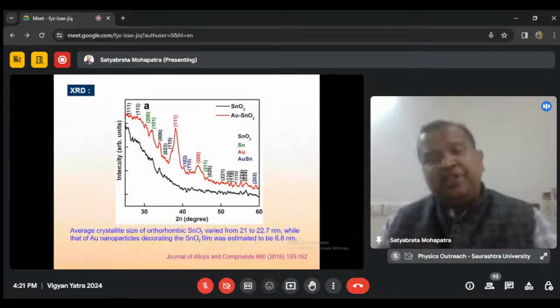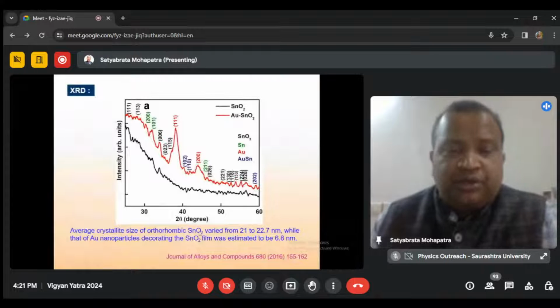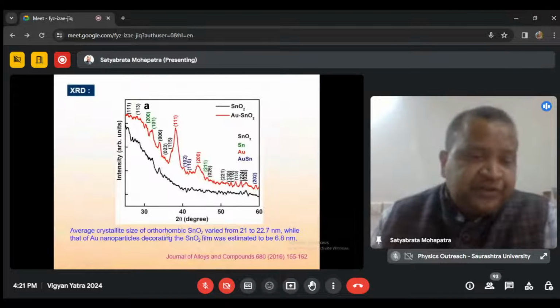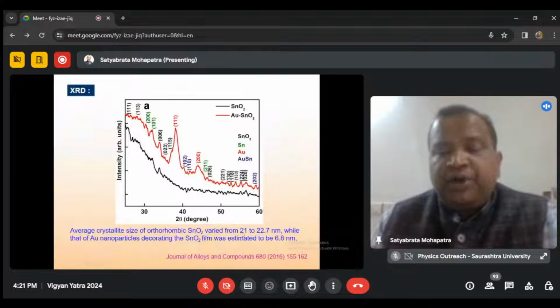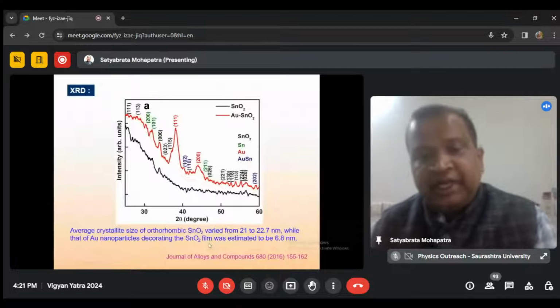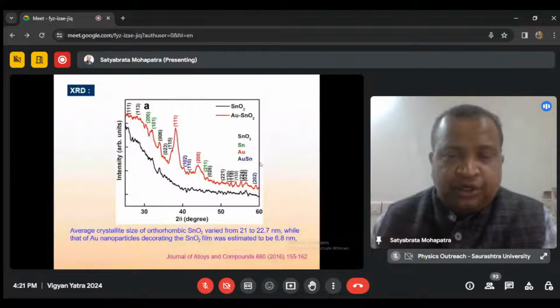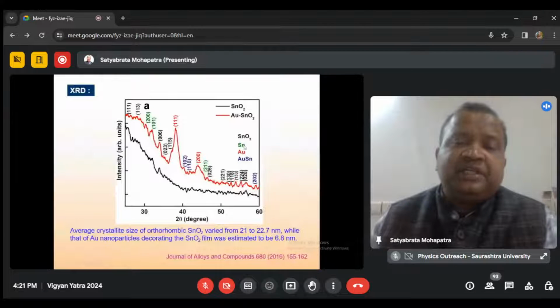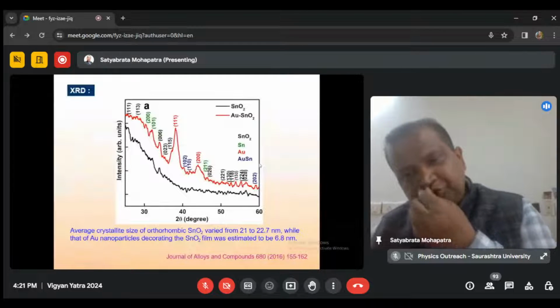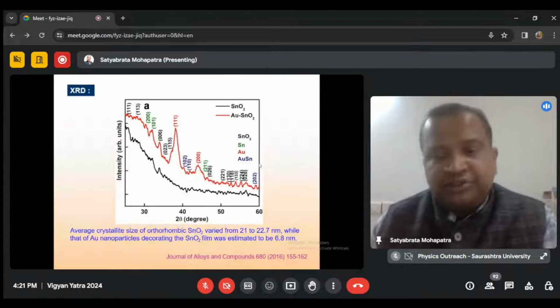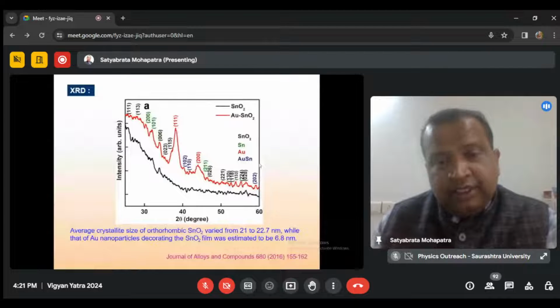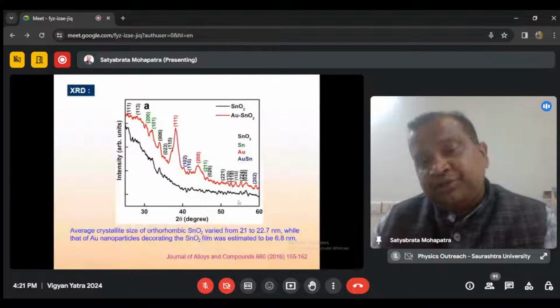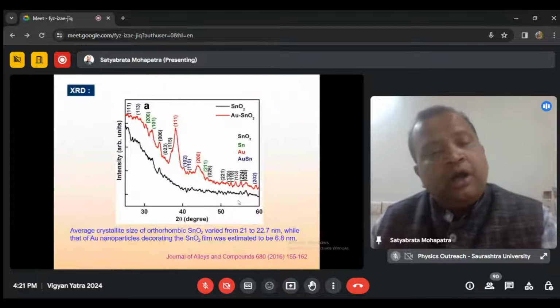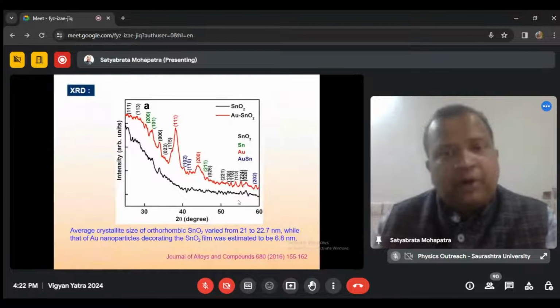And the XRD again shows that we have orthorhombic tin oxide, and the crystallite size of this orthorhombic tin oxide varied from 21 to 22.7 nanometer, while that of the gold nanoparticles decorating the tin oxide film was only 6.8 nanometer. In addition, because we went for carbothermal reduction as a technique, there are additional peaks of tin and gold tin oxide, because the approach we wanted was creating Schottky junctions. You know that these metal semiconductor junctions will be beneficial for improving the sensor response. That was basically the goal.